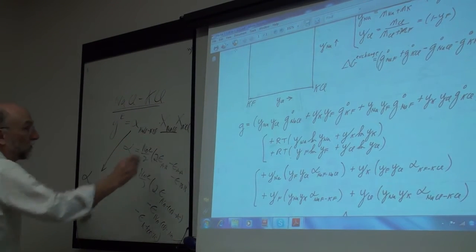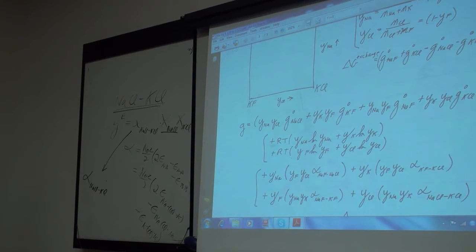And the mole fraction of sodium chloride in that binary system is the site fraction of sodium, the same thing as the mole fraction of sodium chloride if the other lattice is completely occupied by chlorine. And the mole fraction of KCl becomes the mole fraction of potassium. So that is how you would write the binary interaction, the second nearest neighbor interaction in that binary system.